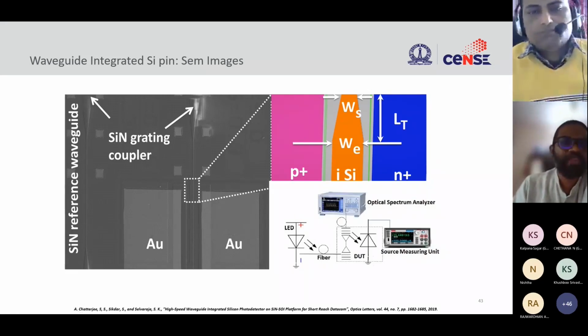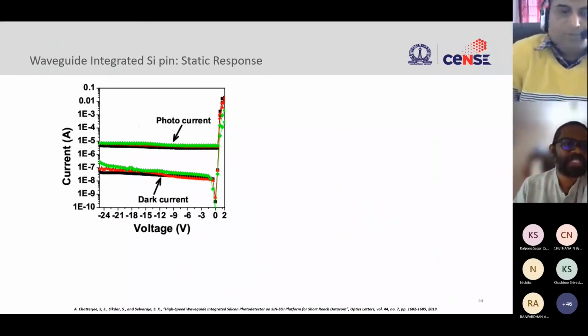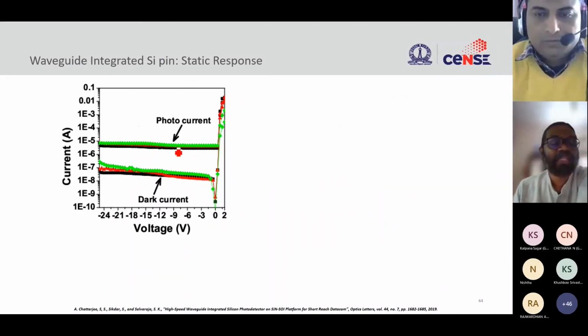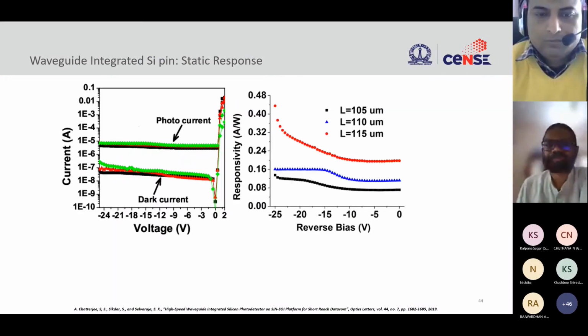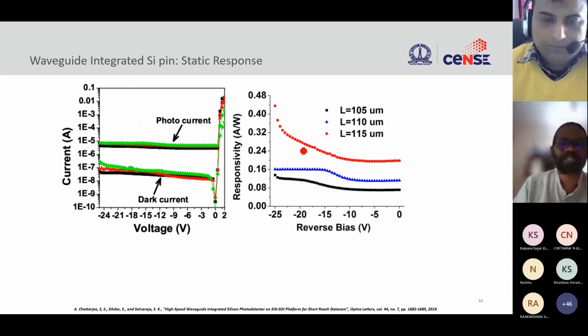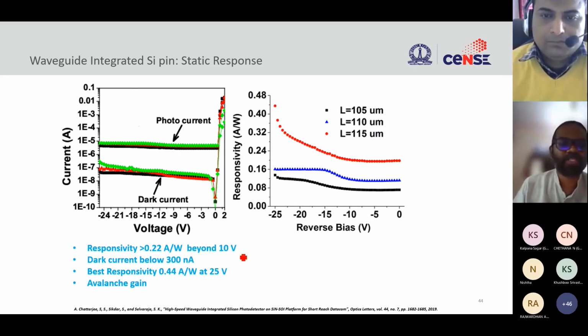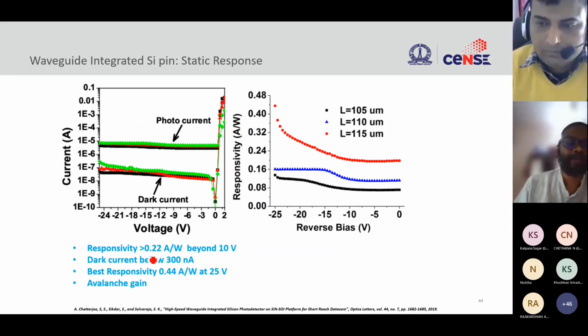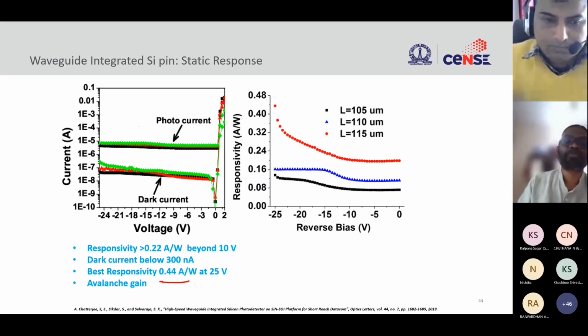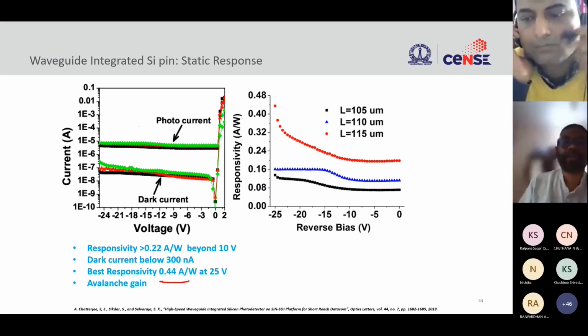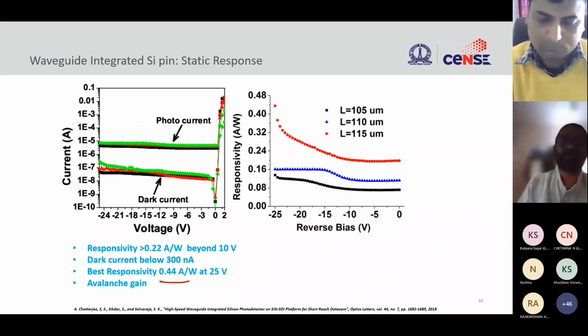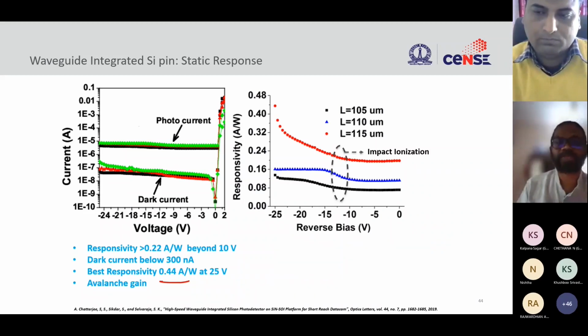We did IV characterization of it, and you can see here, this is the static measurement where you can see the dark current, and this is the photocurrent, after shining light. And you can see here we are already getting responsivity over 0.22, 0.23, right, at higher reverse voltages, of course. And we were able to already show a responsivity of 0.22 amp per watt in a guided wave system. And the best responsivity we were able to get was 0.44, but at a higher voltage, right? So this is already better than what is state of the art before, right? So we were able to show that it is possible to do this.